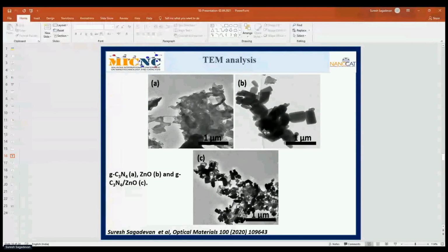Similarly, you can see the TEM image of zinc oxide. It has a nanorod shape, hexagonal or cylindrical, which confirms the hexagonal wurtzite pattern. And then you can see figure C very clearly. In the composite, we can confirm the successful formation of zinc oxide with graphitic carbon nitride, as the nanorods are embedded in the sheet-like morphology, indicating that the sheet-like layer structure of graphitic carbon nitride is retained even in the composite. Finally, the sheet-like structure of the composite indicates the availability of a higher surface area. Why does this kind of material have higher photocatalytic activity? Because the surface area is larger, which enhances the photocatalytic activity.